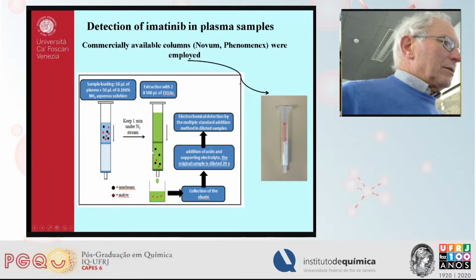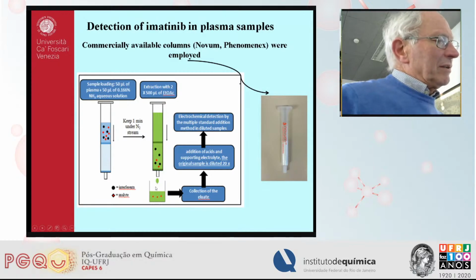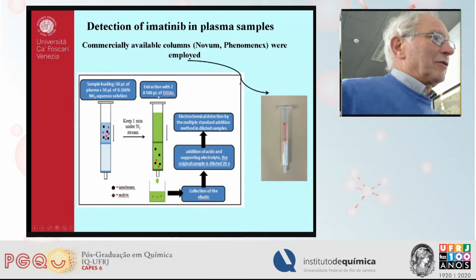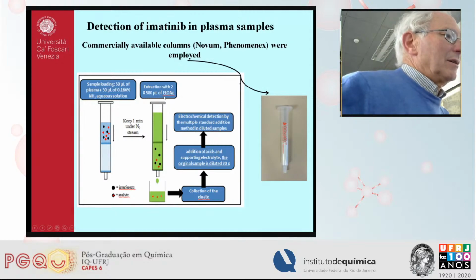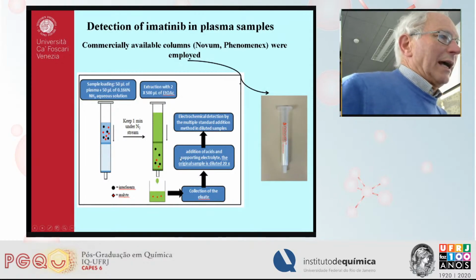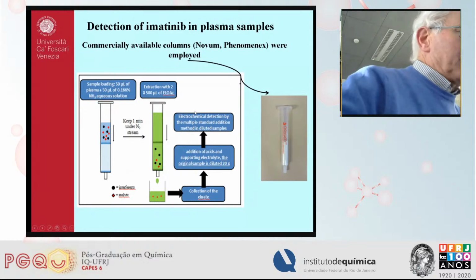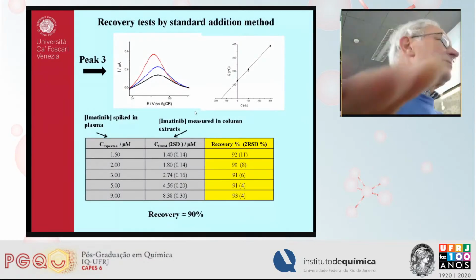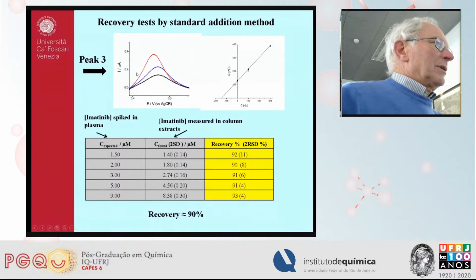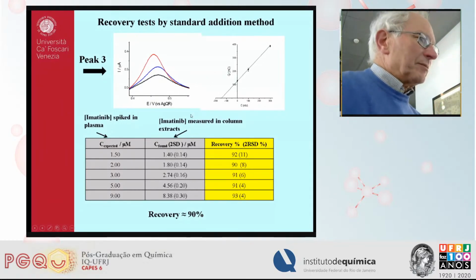Of course, once you get the liquid extract with the ethyl acetate, you should add the supporting electrolyte, acid, and so on, in order to perform the electrochemical measurement. Again, in this case, it is shown the results that we obtained for peak 3. This is the amount of imatinib present in the plasma, and this was determined by standard addition to obtain the concentration.